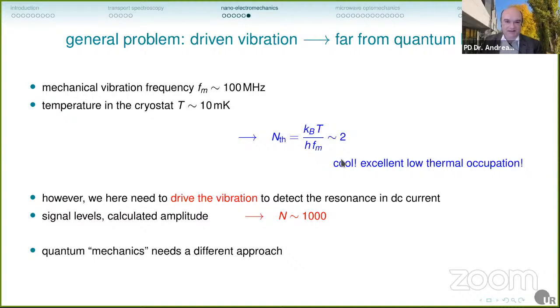The problem is that for our mechanical resonance detection that I've shown so far, we need to drive our vibration. And that destroys this nice number, because we drive the vibration. We can estimate from the signal levels the amplitude of our mechanical resonator, and then we end up somewhere around n is 1000 at least. So that's quite far from the quantum limit. If we really want to do quantum mechanics, we need to try a different approach.